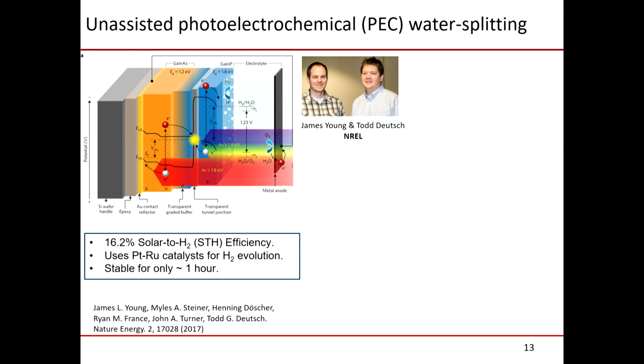Now, there's a few other things that we can do with these materials, and Ismaila gave a great talk on solar photoelectrochemical processes. We've been collaborating with NREL in this domain, so this is some work from them that we weren't involved in, where they set a record at the time a few years ago of 16.2% solar to hydrogen production. They're taking tandem III-Vs and putting on a platinum ruthenium hydrogen catalyst, and it worked. It was one of the records out there, and it was stable for only an hour, which is pretty standard in this field. It's actually really tough conditions in acid. You're dunking these semiconductors. But the good news is that it did work for that time scale.